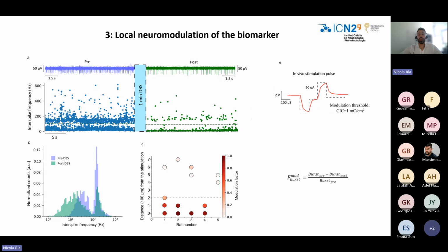This modulation is also very localized because we quantified the modulation factor of the brain at different distances from the stimulating source. And what we observe is that when we stimulate in place or after 100 or 200 micrometers, we have a modulation factor of almost 1, so perfect modulation of the burst. While when we go farther, 400, 500 micrometers, the modulation factor is close to 0. So this means that the current is focal and the modulation is localized around the stimulating electrode.